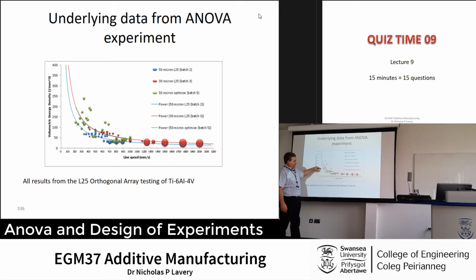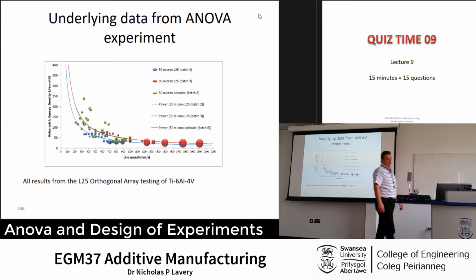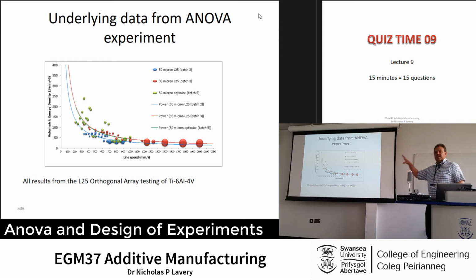And you see as you get the high speeds, you also result in the high porosity. You have an area of smaller porosity around here, so your line speed is about 600, and your energy density is around about optimal, around about there. And then you've got, again, high porosity happening up in this part here, with the low line speeds and the high energy density. But all of that data that came into there was done through a set of orthogonal arrays, done repeatedly over a number of different tests.